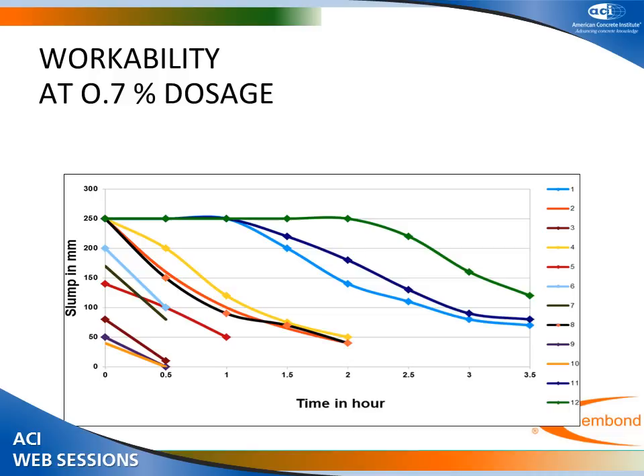This is a combination of all the workability graphs that we have seen before. And here you can see at 0.7% dosages, all these polycarboxylate based ones, that is the green one is 12, that is the slump retention type. And the dark purple one, that is the normal WR1. And the combination of WR1 and SR1 are giving very good workabilities. At the same time, number 4, and that is, I think, the 75-25 combination, is also giving a good slump curve there.